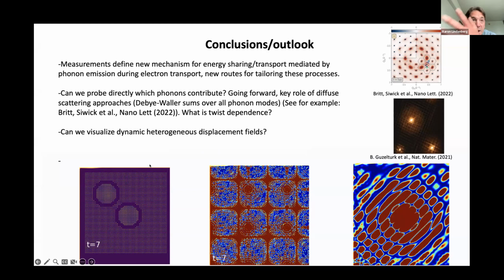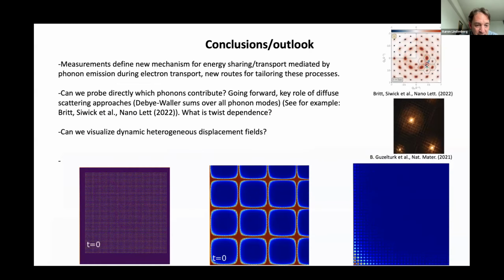So in these experiments, I already mentioned at the beginning of this talk, for example, that in these 2D layers you have all kinds of heterogeneous distortions, local displacement fields, varying on the nanometer length scale, mediated by interlayer interactions in these systems. So in this simple model here, this is just a simple Python experiment where you take a 2D layer and imagine that I have two local distortions dynamically expanding, for example. And so let me actually try to play it.